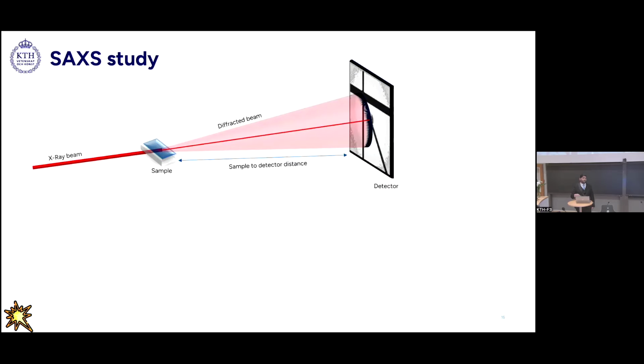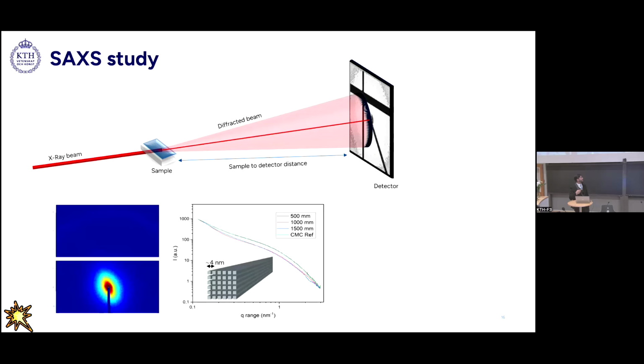Now, if this were true, then we would also have a little bit of surface fibrillation as well as nanopores opening up. For that, we did some SAXS measurements. This is what a typical SAXS profile looks like. After all the post-processing, what we ended up with is a SAXS curve where we tried to fit the autocorrelation functions and SCF so that we can get the actual computational fit for the SAXS data.